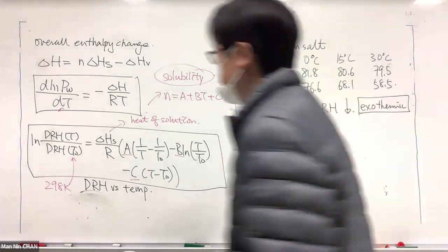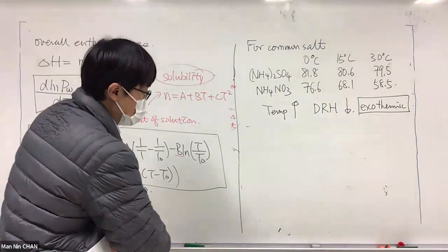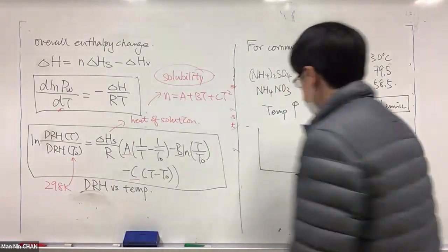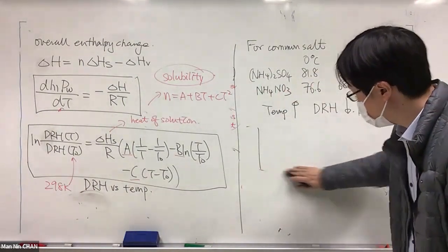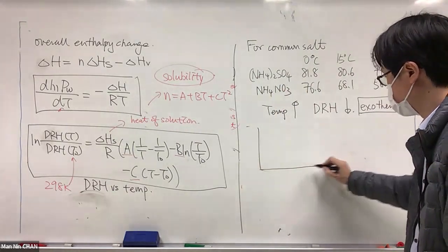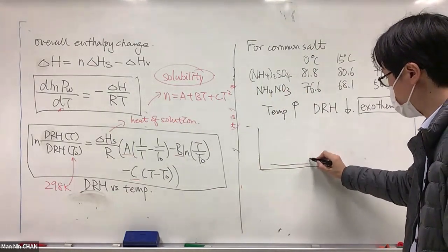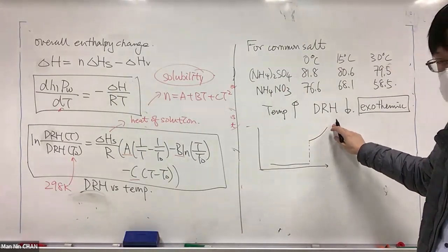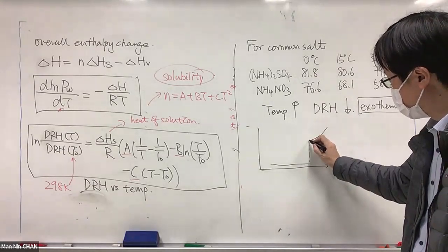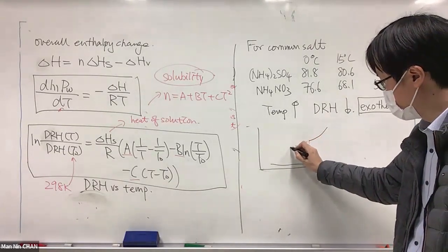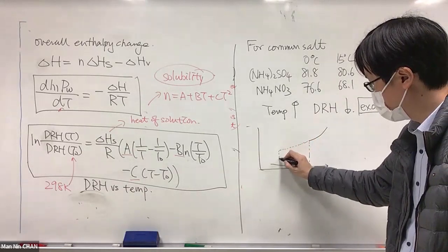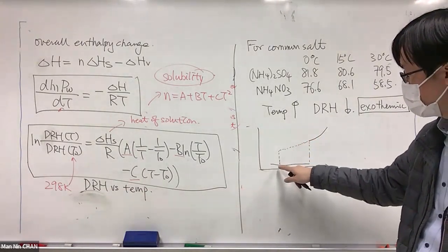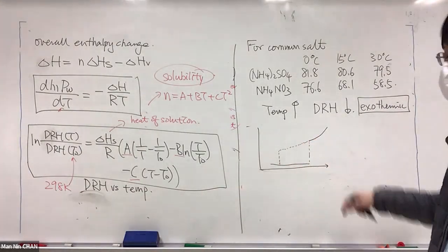Okay. So now we have this. You can see here, if you have a single species, for example, sodium chloride, then you expect a sharp change, and then you have a continuous growth when you increase the RH. When you decrease the RH, it will not crystallize until you have a supersaturated solution, and then at a critical supersaturation it crystallizes and goes back to solid here. So this is a single species.